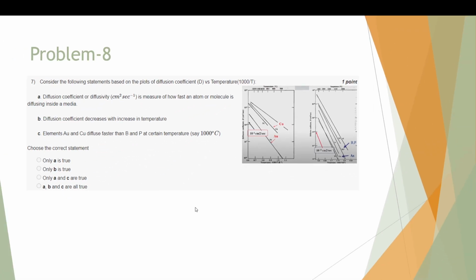Whereas for substitutional impurities like boron, phosphorus, arsenic, the diffusion coefficient is lower because we need to overcome the Ea barrier, right. So, this is the initial, this is final. So, the activation energy will be higher because for the impurities to move in substitutionally, the silicons have to be displaced from their position. So, there needs to be vacancies. So, based on the defects in silicon, the activation energy required for boron and phosphorus to diffuse is higher. So, diffusion coefficient is a measure of how fast an atom or molecule is diffusing inside a medium.